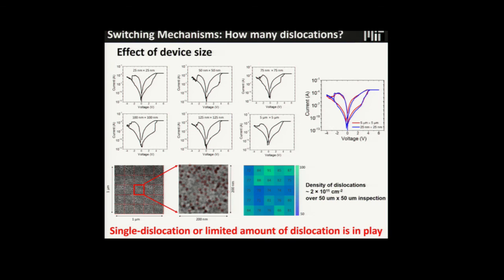Then what's another very interesting thing? The switching mechanism. You may question: there must be random dislocations, so many dislocations. How can just one single dislocation make this device operate? The answer is you don't have to worry about it. If you inject silver into many of these dislocations, there is only one dominating dislocation that switches. How could we prove it? We made devices with different electrode sizes, from tens of nanometers to the micron scale. They all operate the same way, meaning that there is only one or a few dominating dislocations which have a role in switching.